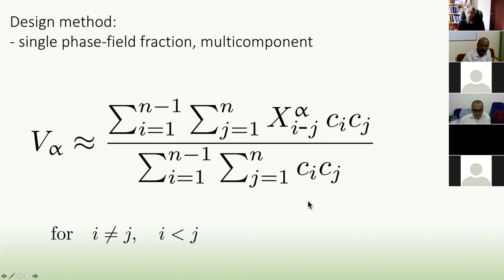And then you feed it into exactly the same form of equation as the melting temperature, where you've calculated the alpha single phase field, let's say for iron and manganese, and these are the concentrations of iron and manganese in your multi-component alloy, and then you divide by those concentrations, and you do this summation for every binary combination, so iron manganese, iron chromium, iron cobalt, and so forth and so on. And that gives you a parameter which says, look, I have a good chance or a bad chance of hitting a single phase field of alpha in my multi-component system, depending on the magnitude of this parameter here.